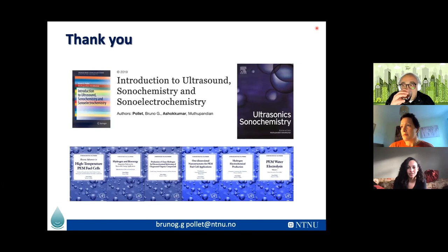Sam Sullivan is also asking, what level of control can you have for the nanoparticle synthesis through sonochemistry? With the paper that we just published, we showed that you could control the radical formation over time. You could say, I want to produce X amount of H radicals, and that would give you that amount and also the size of your nanoparticles. I could send you the paper, but you could effectively play with the sonochemical efficiency, and guesstimate the radical formation that would give you a certain size of nanoparticles.